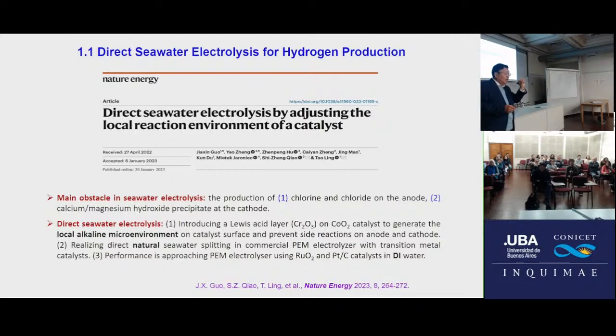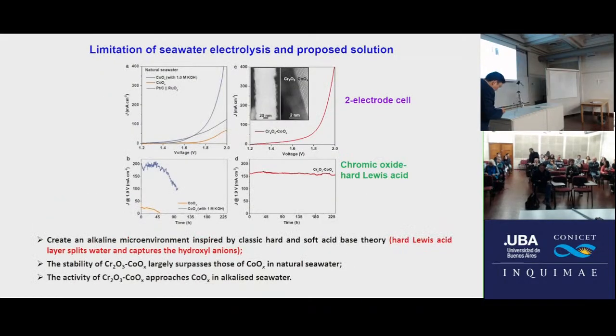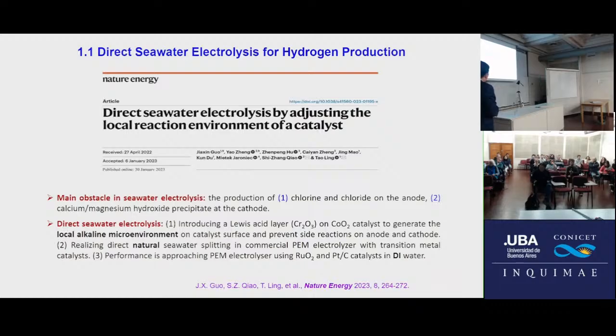It can attract OH minus produced during water splitting. Yeah, during water splitting we produce OH minus. That's why they absorb on the Lewis acid surface. Okay, so in that case you can see we can make the local environment at the catalyst surface alkaline. It means the pH value is very high. It's 14. I'll give the reason later. In that case, we can prevent side reactions on the anode side and the cathode side.